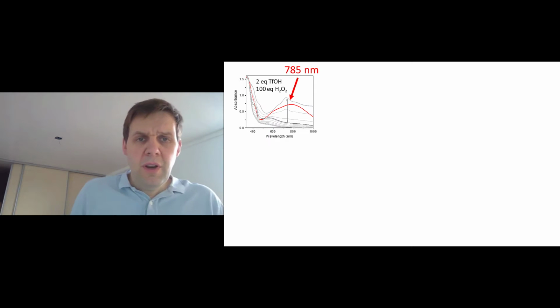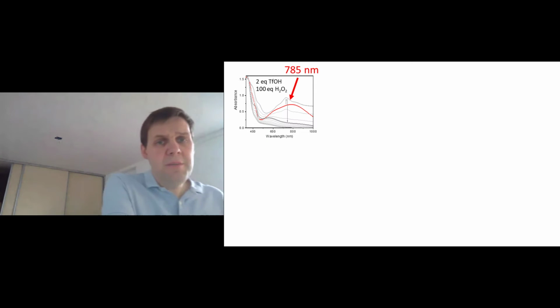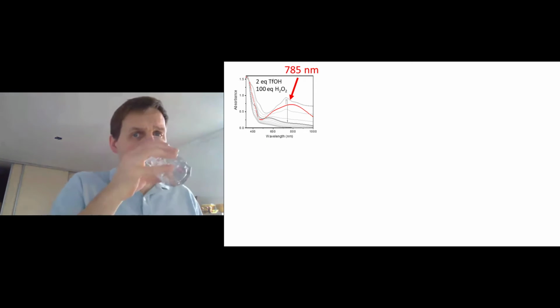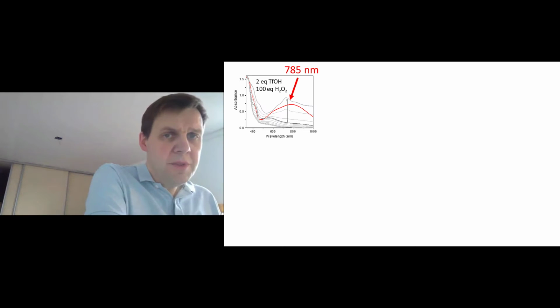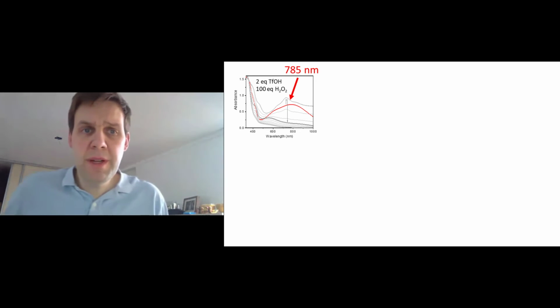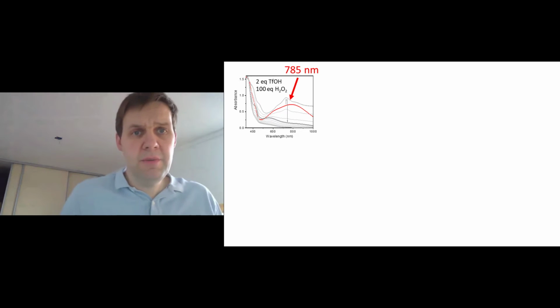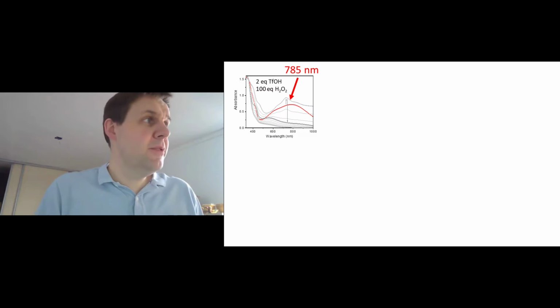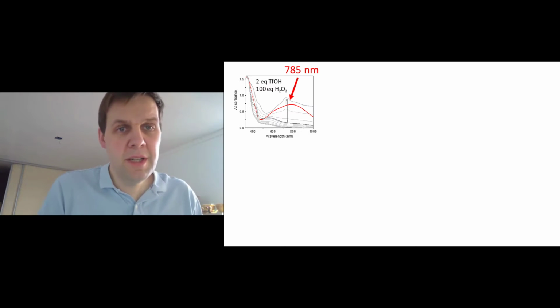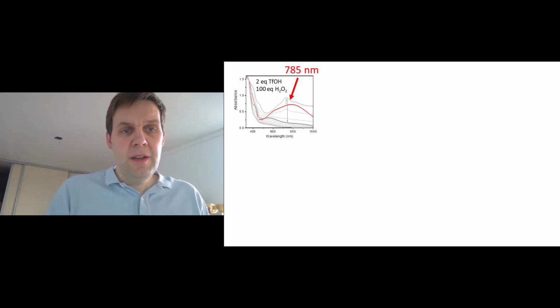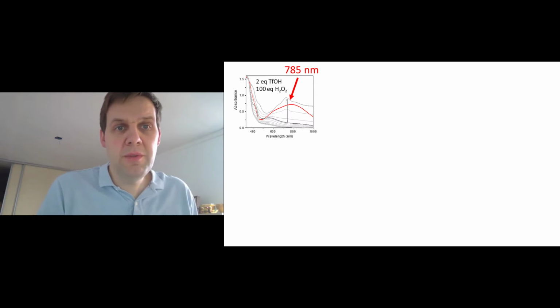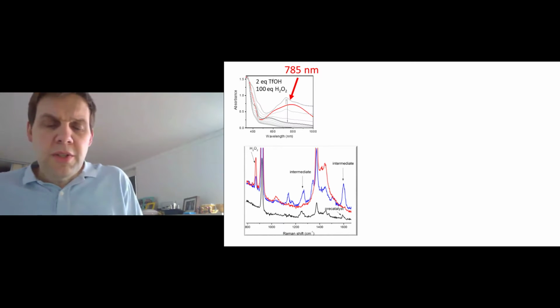So the question is, what are these very strong absorption bands that appear during the reaction? Now, the catalysis is done with 2 equivalents of triflic acid with respect to the complex and 100 equivalents of hydrogen peroxide. And this actually confused us for quite a while. Imagine a year and a half of a student working on this, until we just decided, well, what happens when you add 1 equivalent of hydrogen peroxide? If you don't add the acid, nothing happens. But if you have the acid present, something happens. So what happens? Well, you see new species.